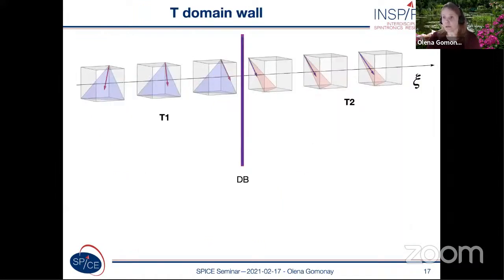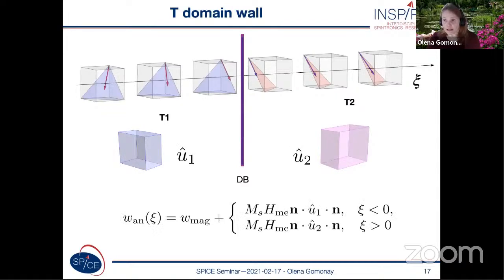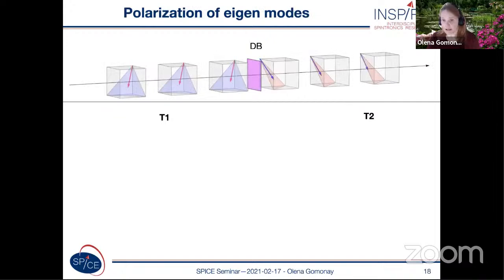So if we consider a domain wall which separates 2 T-domains, so these domains are called twin domains or T-domains, we found out that in this case, not only the orientation of the easy axis is different in the left and right domain, we find out that also the orientation of the easy plane is different. So what can happen then? Then we understand that in this case, we again have a space-dependent anisotropy field, with space dependence of all possible directions defining easy and hard magnetic axes.